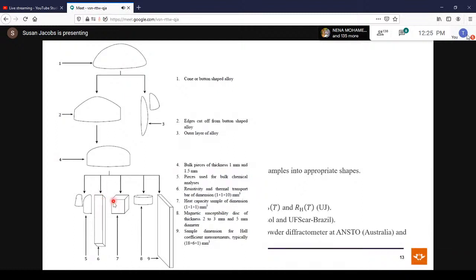Now, for specific heat measurements, what we do is we apply a heat pulse and we allow the sample to relax, and then we do the measurement. So you don't want a sample that is too big, because then the relaxation will take too long. Also, you want the sample to have good contact with the platform. So the ideal shape for a specific heat measurement would be a cube of side 1 millimeter.